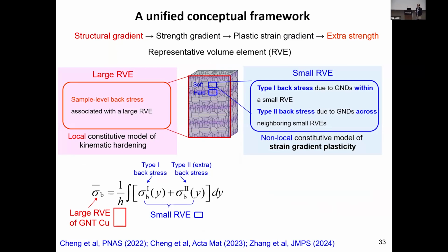We did a more systematic study to really resolve the back stress distribution within the heterogeneous systems, right? So you have the sample-level back stress effect, but we also need to recognize the spatial distribution of back stress. It evolves with load. It's highly non-trivial to quantify. Now, we can use the integration of computational modeling and experiment to clearly understand the local back stress and also the gradient effect due to the neighboring RVE, the representative volume element. They produce additional back stress effect.